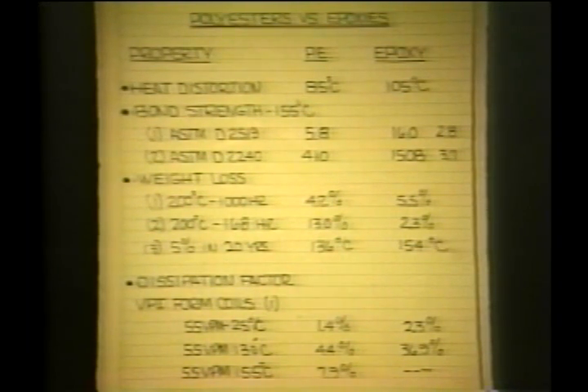And in the next couple of slides we look at, we're going to present just some of the principal properties that are frequently discussed. And what I've done here is to try to take data reported from different sources so as not to slant it one way or another depending upon what somebody may have been trying to prove or the point that he was trying to make. But there is common agreement that the polyester resin normally has a lower heat distortion temperature than the epoxy. You can see the 85 versus the 105 degree difference.